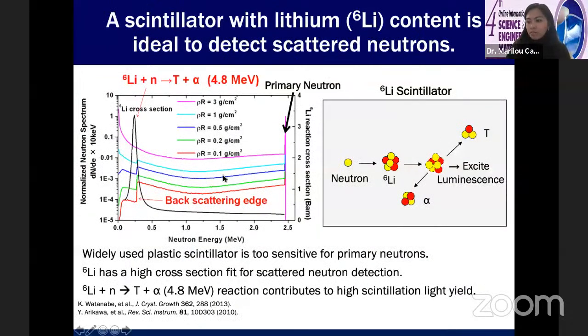If we can see here, this shows the energy spectrum of the neutrons. We can see these primary neutrons at around 2.5 mega electron volts. It's high energy, but it's also intense. So it's quite easy to detect the primary neutrons. But if we look at this lower energy region, we can see these scattered neutrons that are weaker than the primary neutrons. And the detection of these scattered neutrons is quite problematic because they are easily swamped out by these intense primary neutrons.